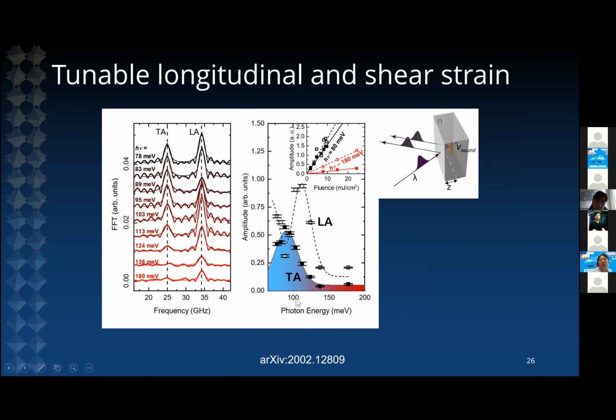And our experiments show that as we tune the photon energy of our source, we can redistribute the amplitude of these two strain waves between a transverse and a longitudinal wave. So when we are close to the resonant peak, we have a mainly longitudinal strain propagation, while when we are sitting on the very top of our resonance, the strain propagation is dominated by a transverse wave. So there is an interplay between longitudinal and transverse strain that is being generated by this pulse.